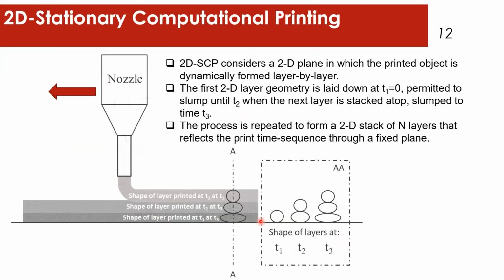That being said, the question is, how can I move from modeling a single gob of material to actually modeling printing? So what I do is, if you imagine that you can only see what happens in this plane AA, this plane is just slicing through some bit of space where the printer is going to pass periodically every now and then. The first thing that you would see is that the first layer will be deposited at time T1, but it won't be until some time T2 that the printer will come back over that layer and deposit the second layer. So at time T2 minus T1, the first layer will slump on itself because it's Portland cement.